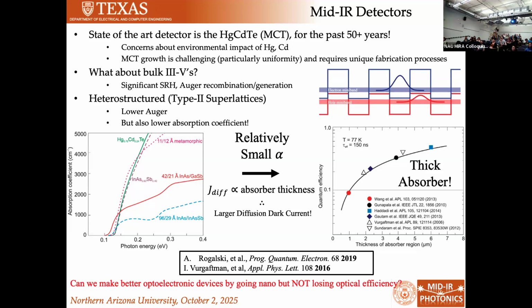Now the problem is, as I said before, what we have in the mid-infrared are very inefficient processes, which means that we don't have very good absorbers, which means that our absorption is weak. So if we want to absorb a lot of the light that's incident on a detector, we have to grow a thick detector. If we grow a thick detector, then we have a lot of noise, right? And so we're improving one metric at the expense of another. But now we have this way of making materials that we know can confine light to very, very small dimensions.